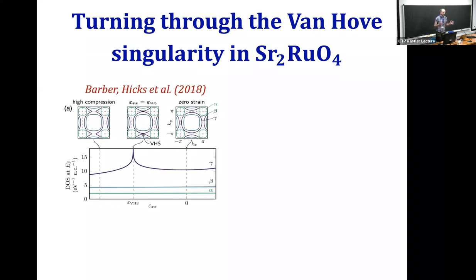All right, so I'll start with this example of tuning a metal to the vicinity of a Van Hove singularity. It's a relatively conventional case, but beautifully, it was actually realized recently in strontium ruthenate 214. It's a very, very clean metal, so it's a very good test case. And what's been done is actually applying uniaxial strain to the system so that we can tune one of the three bands in the system through the Van Hove singularity. This is a very quasi-2D metal, so we can really think about the 2D band structure. And you see that this band, as a function of strain, actually touches the zone edge.